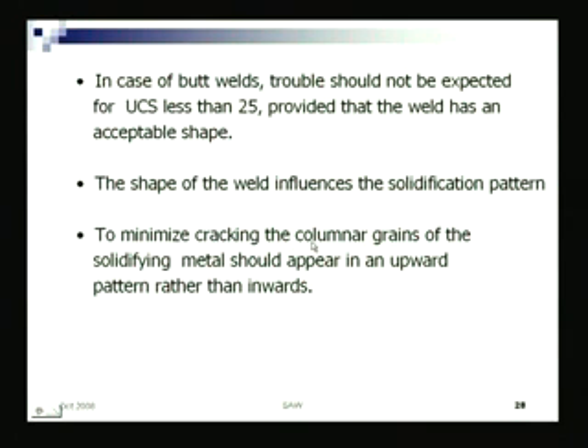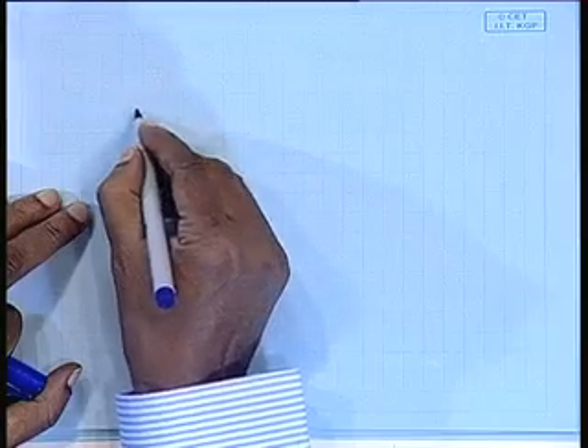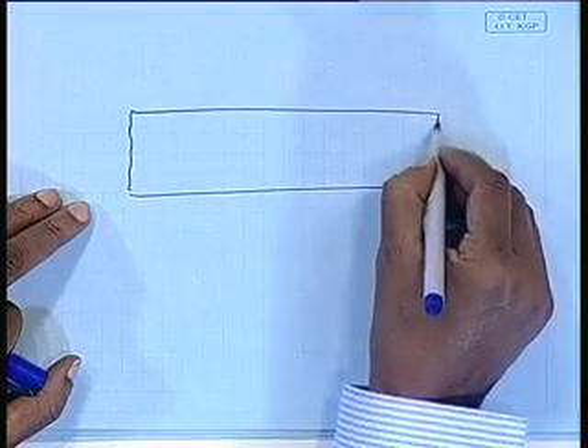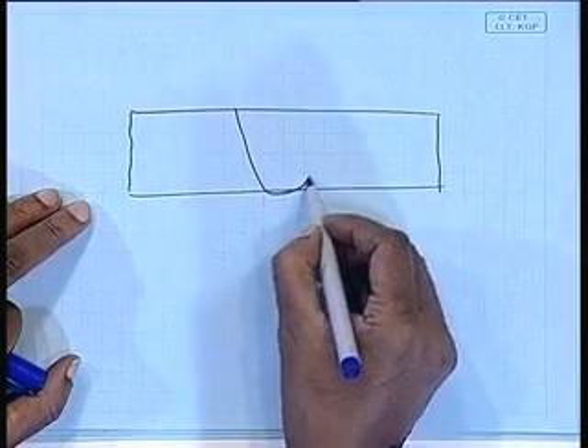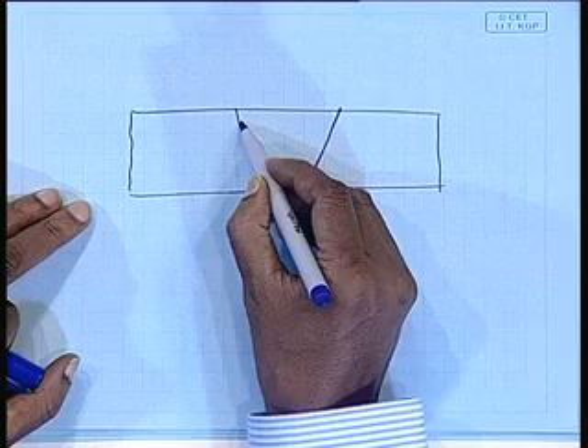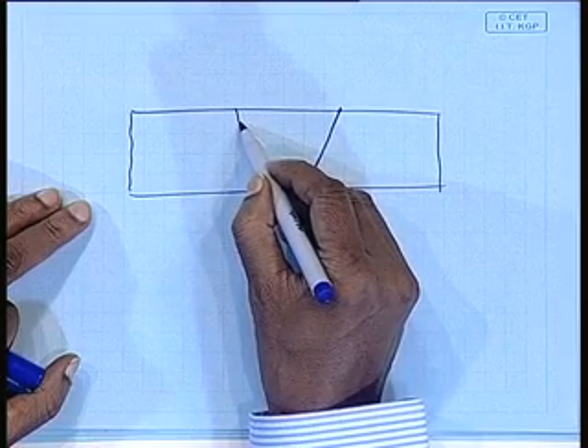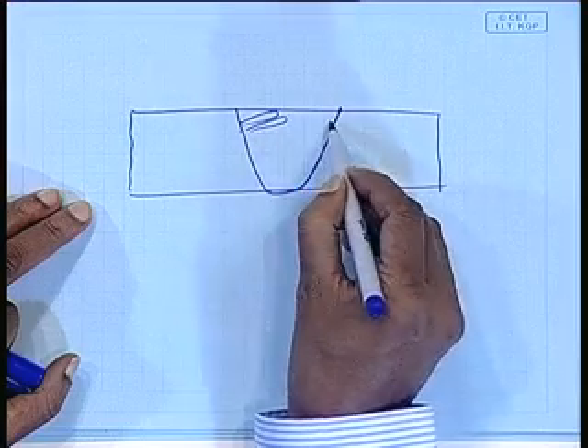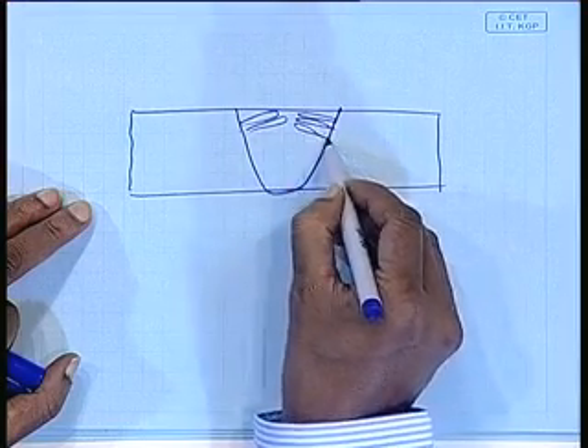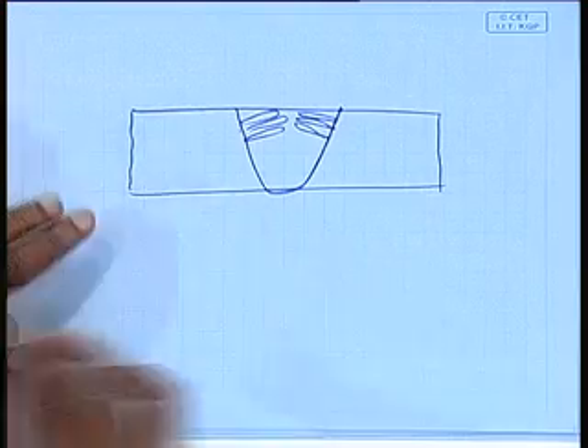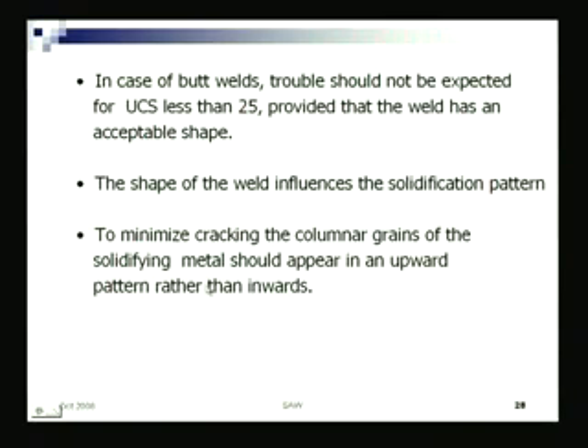To minimize cracking, the columnar grains of the solidifying metal should appear in an upward pattern rather than inward. This is the grain structure, how it should be. When metal solidification takes place in welding, let us assume the fusion zone is like this. The molten metal forms what is referred to as columnar grains, grains like this, elongated type. It should have an upward sort of pattern rather than downward.